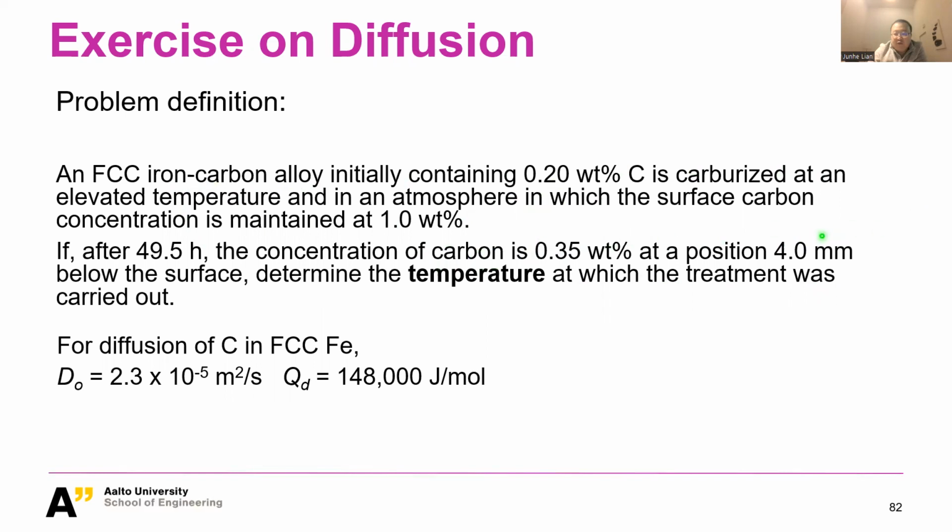About time, position, and temperature. So this is a non-steady diffusion problem. That's the first thing for you to realize. When you talk about non-steady diffusion problem, we're talking about Fick's second law, and you also realize we're talking about the solution for Fick's second law. And the question is asking about temperature, right?